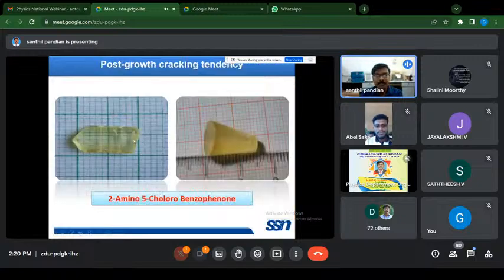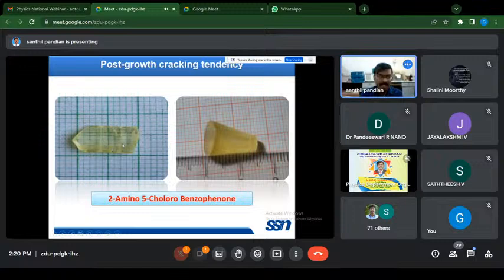Crystals which have a post-growth cracking tendency can be grown without that tendency, which results from the temperature instability in the conventional method grown crystal. A lot of micro cracks appear in the crystals grown by the conventional method. But in the SR method, we have maintained two different temperatures, at the top and bottom portion. So there is a stable supersaturation in the grown crystal, a stable solvent evaporation, and a uniform growth rate. There is no chance of solvent inclusion in the SR method grown crystal.